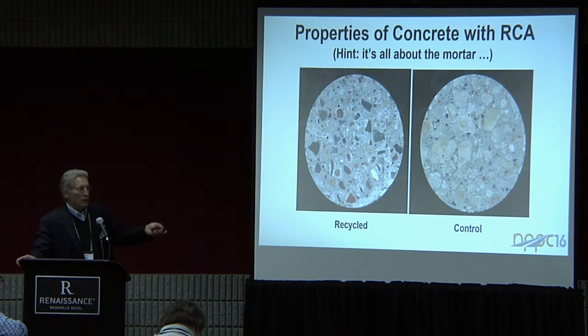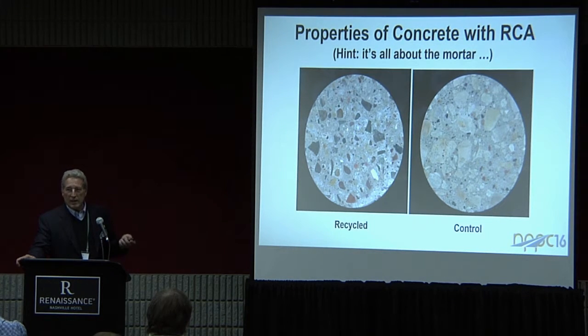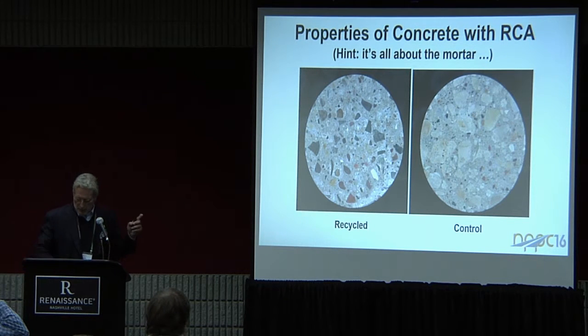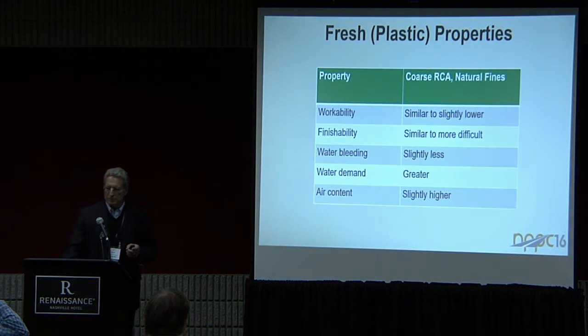The lighter colored mortar is the reclaimed mortar. But the total mortar content over here is much higher than the total mortar content over here. And as a result, you're going to tend to see higher absorptions, higher shrinkage values, higher creep values if you're in a structural application, things like that. So you have to treat it like an engineered material.